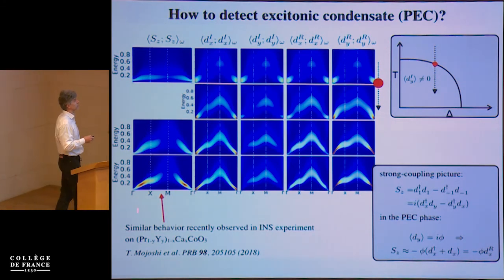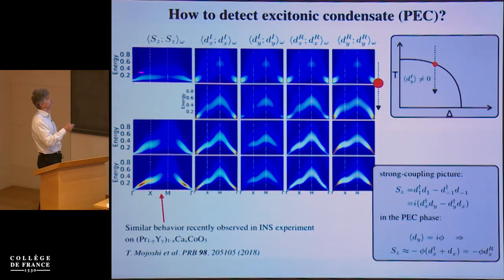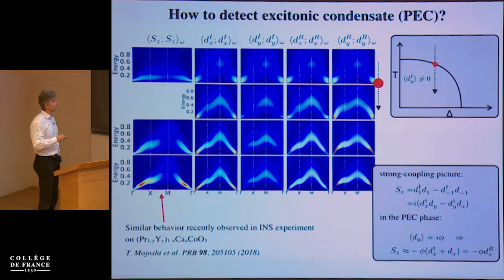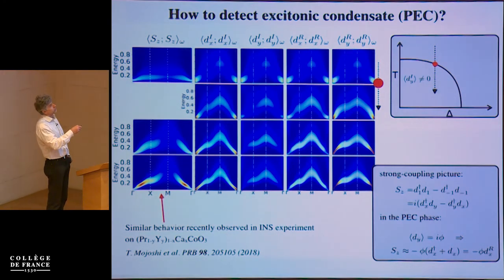So what we think is the most promising idea is to use this spin structure factor, because as I showed you before and show you here again, there is a qualitative change of the spin response when we go from the normal state to the ordered state. In the normal state, you see essentially local moment-like response of the thermally excited high spins.